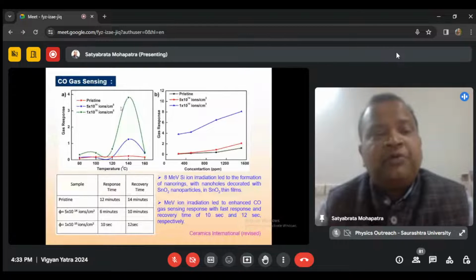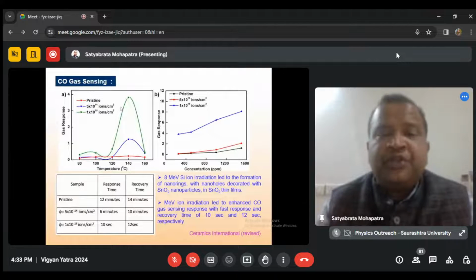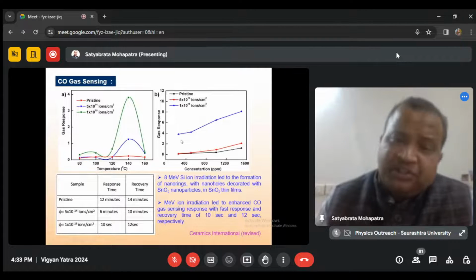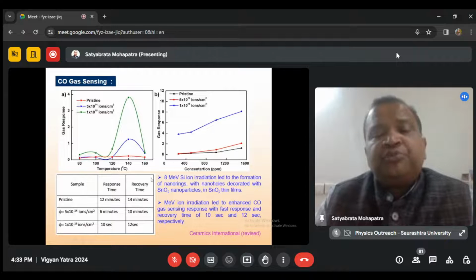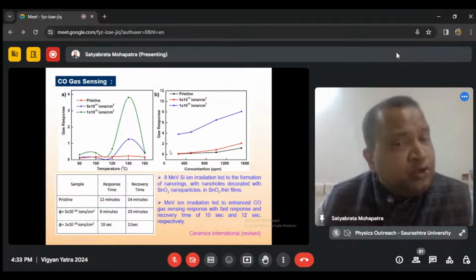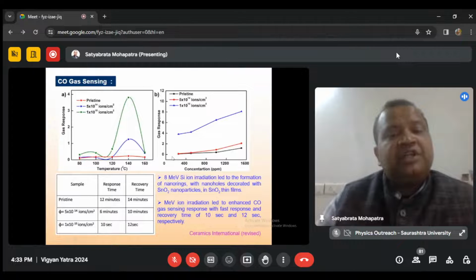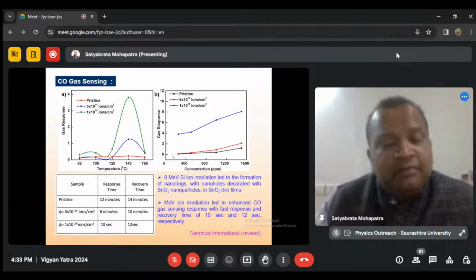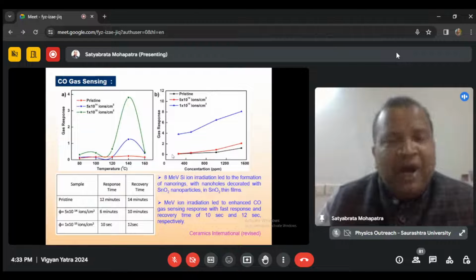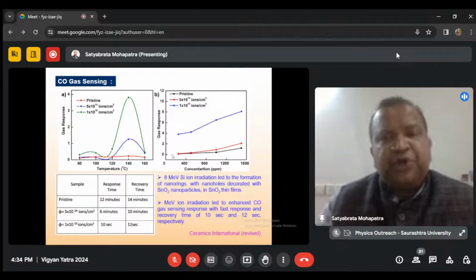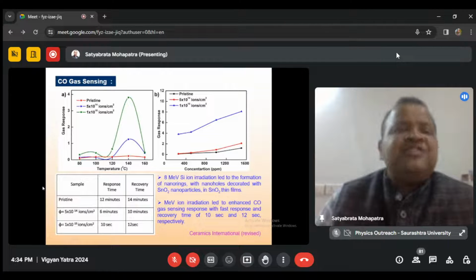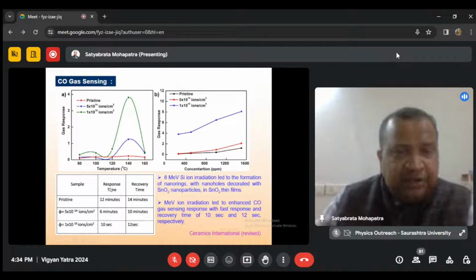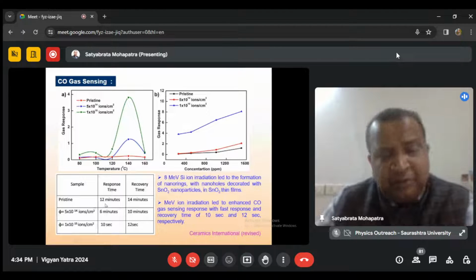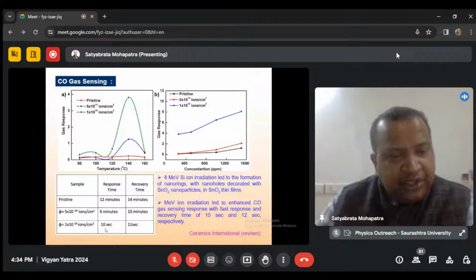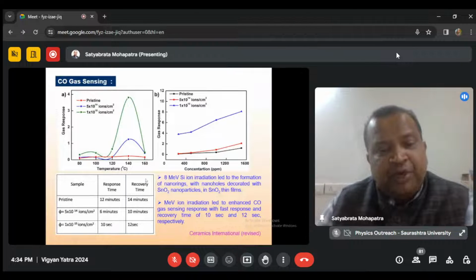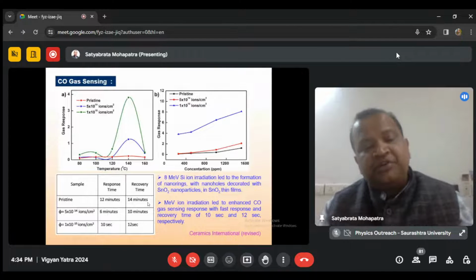The difference is huge. You have very much improved gas sensor response, and of course as you increase the concentration, this sensor response increases, you know that, but we should focus on lower concentrations of carbon monoxide to save lives. And even at lower concentrations, you can see that between the nanoparticle film and the nano ring film there is a remarkable difference. So the nano rings, if you produce them, lead to remarkable enhancement in the sensor response, and also you can see it in the response time and recovery time. In the pristine film, the response time is very large, 12 minutes. But if you go to nano rings, it is just 10 seconds, and the same is true about recovery time. From 14 minutes, the recovery time drops to 12 seconds.